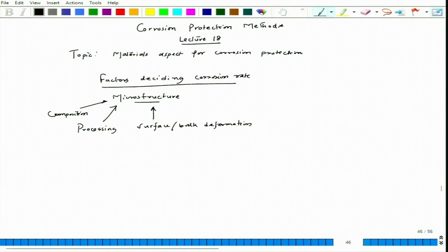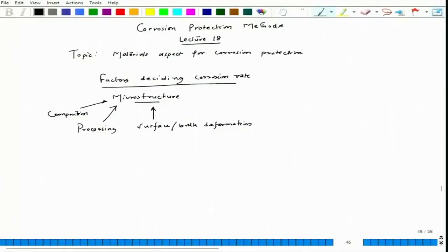Here, with surface and bulk deformation, we have to remember that even bulk deformation would lead to a change in the surface microstructure, and surface deformation would also lead to a change in the surface microstructure. Since corrosion is a surface phenomenon, whether it is bulk or surface, if there is an influence on the surface, it would definitely have an effect. So these are the factors which will lead to some change in the microstructure. And here in microstructure we are talking about grain size distribution rather than no grain or amorphous. We have discussed the amorphous part in our last lecture. So let us talk about the grain structure, or grain size rather.